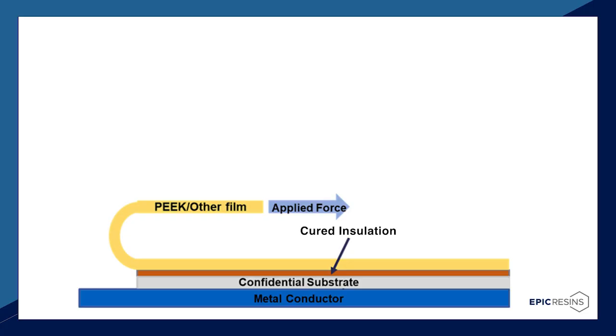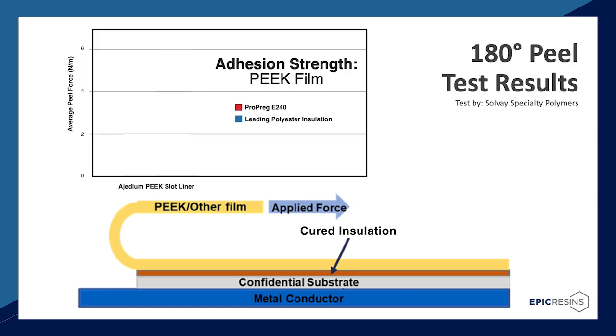As you can see from the illustration, a PEEK film is adhered using ProPreg E240 or polyester insulation to the metal conductor substrate. The PEEK film is then pulled at a 180-degree angle while the metal conductor is held in place. In the 180-degree peel test, you see in the graph that E240 obtains at least double the adhesion compared